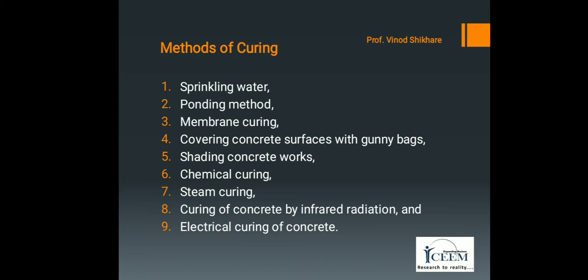The second method is the ponding method. Ponding method is mainly adapted for surface members such as pavements, floors, slabs, roofs, and sidewalks. It is a mostly used method of curing. In this method, a small dam of earth or water-retaining material is placed around the perimeter of the surface. The surface is covered for 24 hours after placing and compacting concrete. The enclosed area is further divided into a number of rectangles and is kept flooded with water. Water is filled in the rectangles 2 or 3 times per day depending upon the climatic conditions.